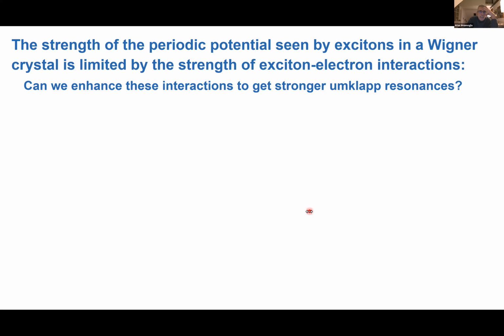The other question is whether we had the chance to look at temperature-dependent transport, and the answer is unfortunately no. Two-dimensional semiconductors are very difficult to contact. There is this large Schottky barrier, and my understanding, though I'm no transport person, is that unless you go to high electron densities, it becomes very difficult to do transport. In the literature you'll see nice transport measurements with 10 to the 13 electrons, or several times 10 to the 12. But at the densities where we see the Wigner crystal, it's essentially impossible to do a transport measurement, as far as I know, and we certainly haven't done it.